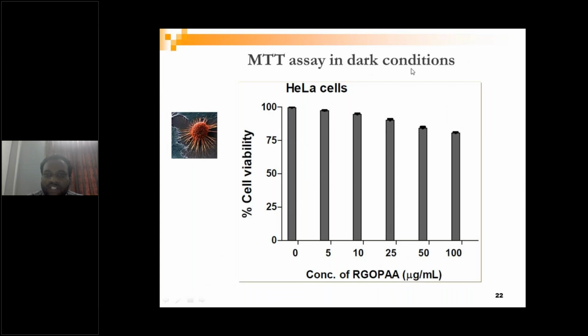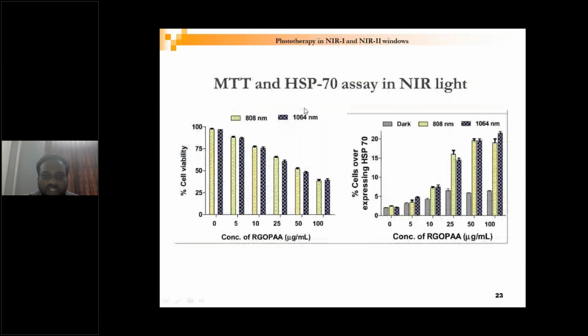Well, here is the MTT assay in both conditions. We added RGOPA to the HeLa cells. In the dark condition without light, you could see that though the concentration has been increased, the survival rate is not affected much. About 80% of cells are viable. Whereas in the presence of light, 808 nanometer and 1064 nanometer, with the concentration there is a decrease in cell viability. But still, this experiment has to be optimized. We can say that 50% or more than 50% of cells are inactive in both windows. Well, as evidence of whether it could generate heat, we have the heat shock protein expression assay.